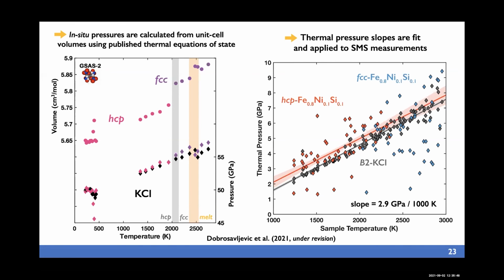Thank you. I have a quick question about the setup at 3-ID-D. Is it similar to what ESRF is doing? No, it's different. It doesn't utilize an iron borate crystal, which needs to be cooled. This utilizes the high-speed shutter, and it selects out the pulse from the hybrid mode, and it illuminates the stainless steel foil, which acts as the source. So the iron-57 in the stainless steel foil acts as the source. That's on a drive, and then one can do conventional Doppler-shifted spectroscopy. Thank you very much, Jenny.